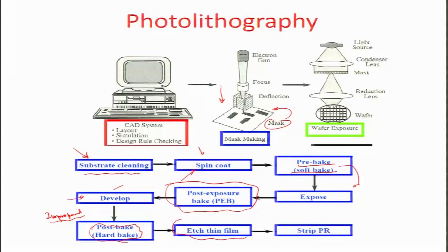You then etch out the thin film, which you are using as a mask. Lithography is typically carried out either for a lift-off end process or for an etching process. Resists are normally used as sacrificial materials unless you want to develop something with the resist itself, like a micro-cantilever. You etch the thin films and then strip out the photoresist, so that you are left with the etched pits on the thin film. The resist acts as an etch stop layer in those situations.